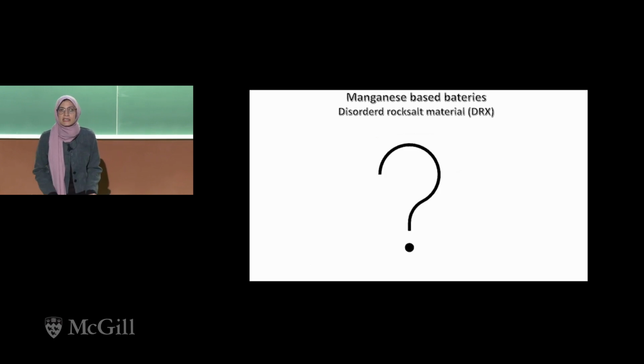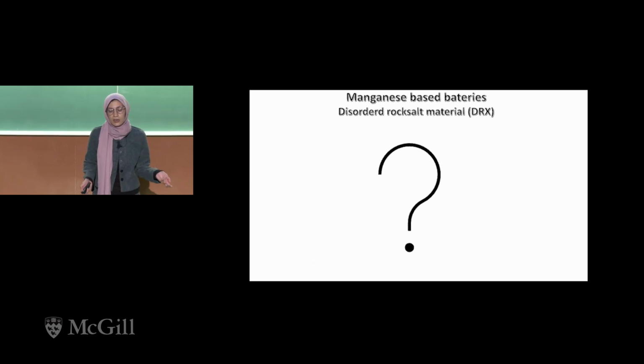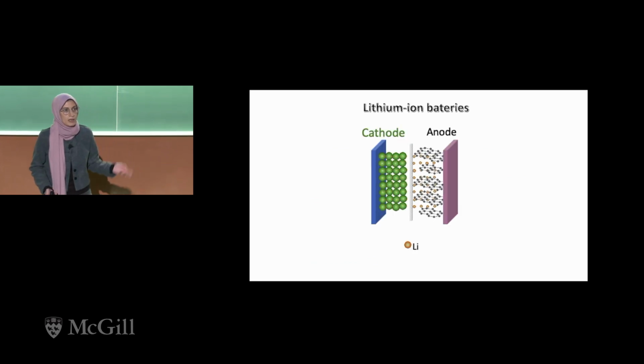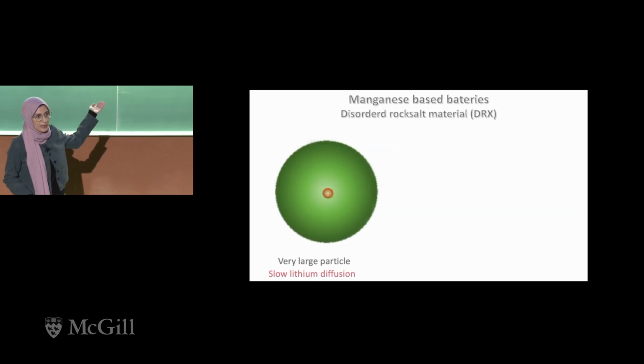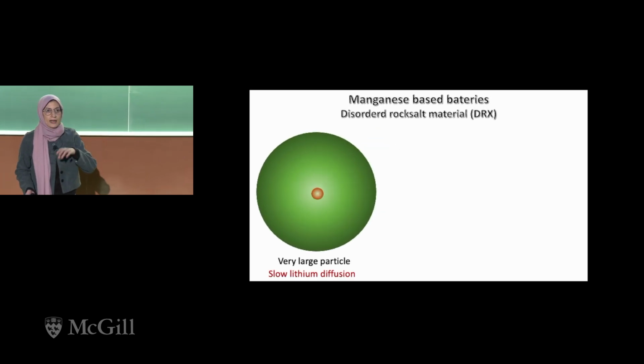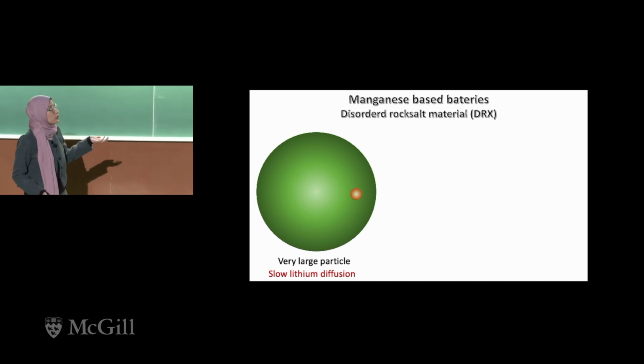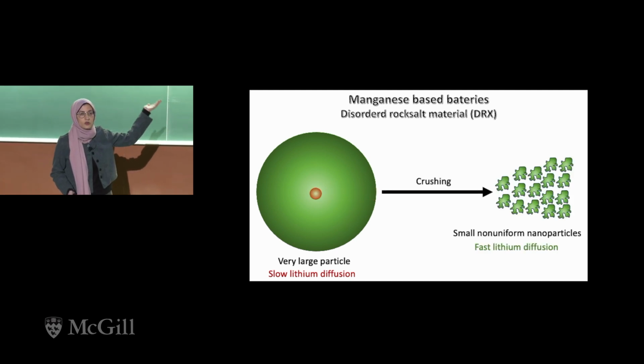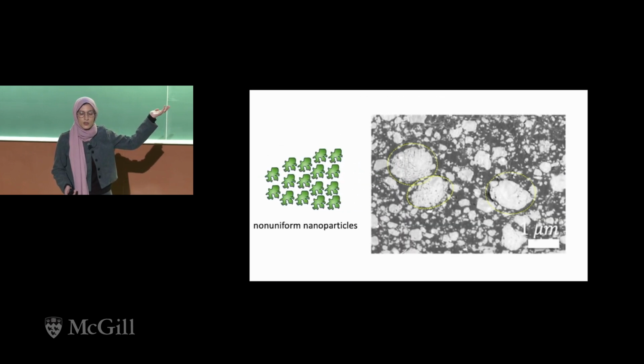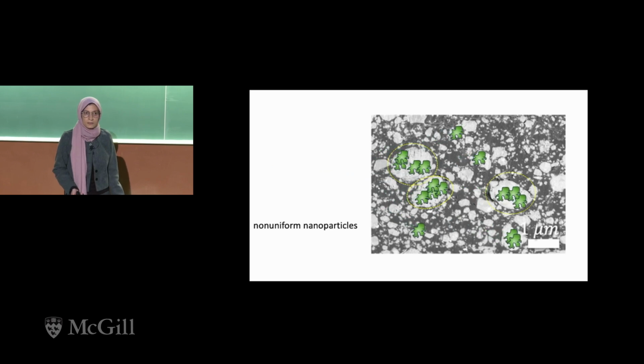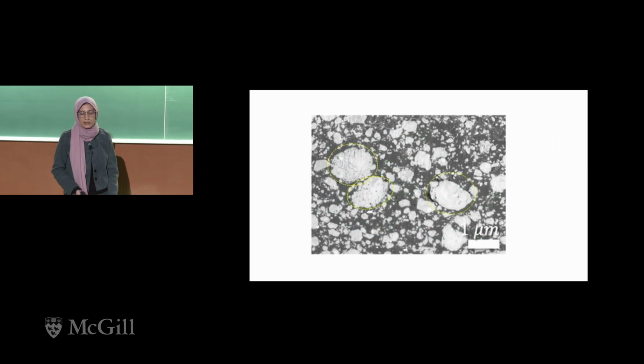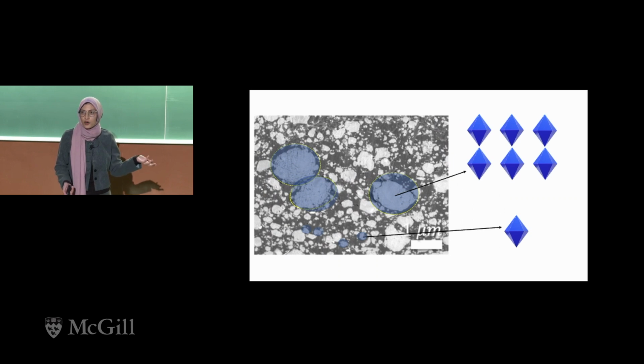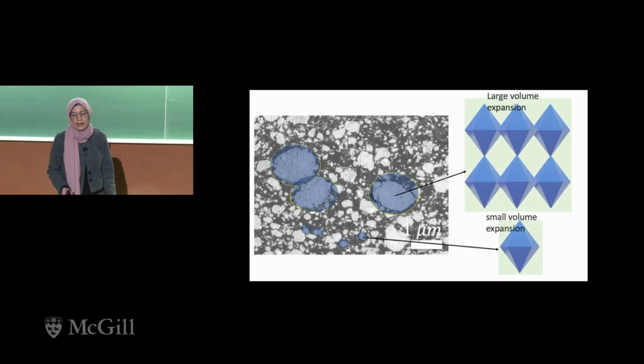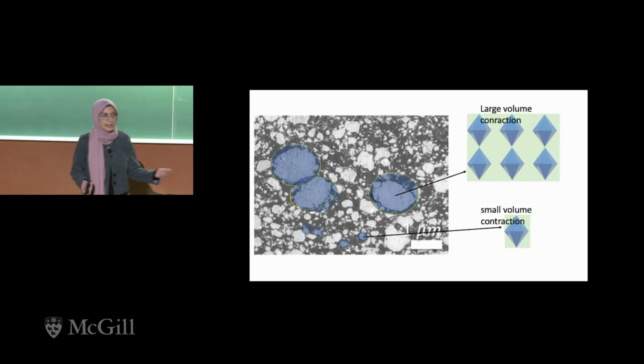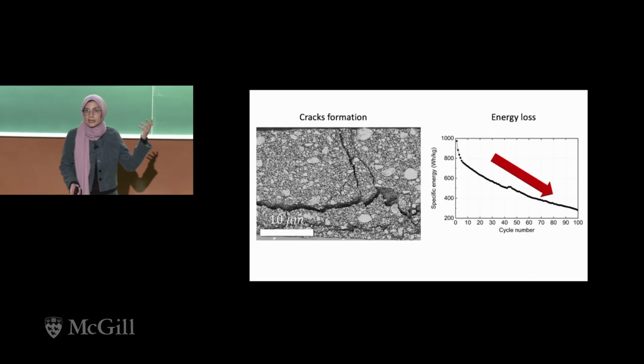So why aren't we using this material? The challenge lies in the particle size. The cathode particle of the manganese-based batteries is too large, which slows down the lithium movement. So what people usually do is crush this particle into smaller ones. However, these small particles with non-uniform morphology tend to agglomerate in the electrode film, producing non-uniform particle distribution and non-uniform volume change during charging and discharging. And this will lead to crack formation and fast energy loss.